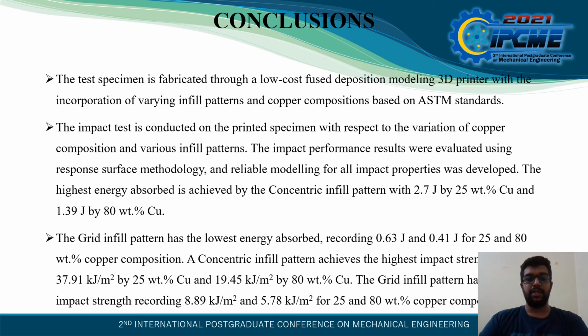The highest energy is observed in the concentric infill pattern using this optimization, 2.7 joule at 25 percent of copper with PLA, and also 1.39 joules at 80 percent of copper with PLA. And also the grid infill pattern has the lowest energy in this process, 0.63 and 0.41 at 25 and 80 percent of copper in the PLA respectively.